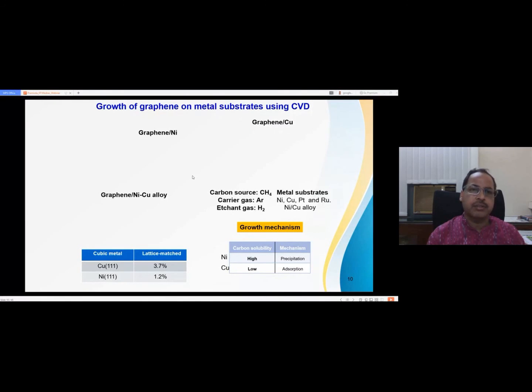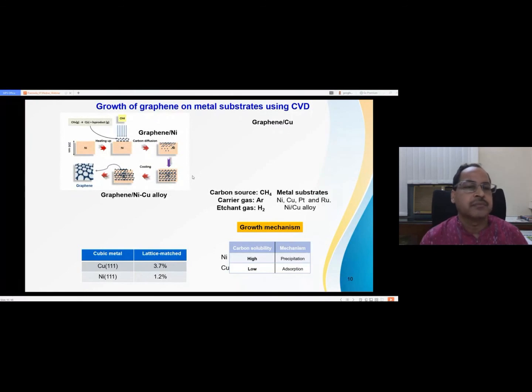So first see the growth of graphene on the nickel substrate. First you take the nickel substrate. Then in the CVD chamber, the input gas is methane, CH4. The CH4 dissociates into carbon and hydrogen or some byproducts. This carbon diffuses into the nickel, and then it is precipitated because the solubility of carbon in nickel is very, very high. So this is called the precipitation effect.